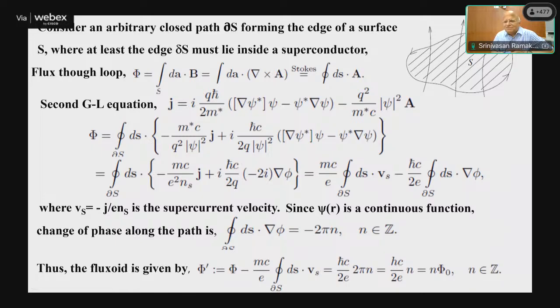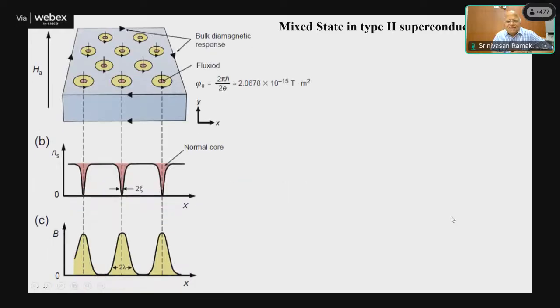And since the magnetic flux can only penetrate in the form of this n phi naught, people showed, actually you can show by solving the Ginzburg-Landau equation, that the magnetic field penetrates in the mixed region in the form of fluxoids. This is a normal region. There is a superconducting current flowing around. And these are what they call vortices. These vortices repel each other and they form a lattice. It's called the flux lattice.